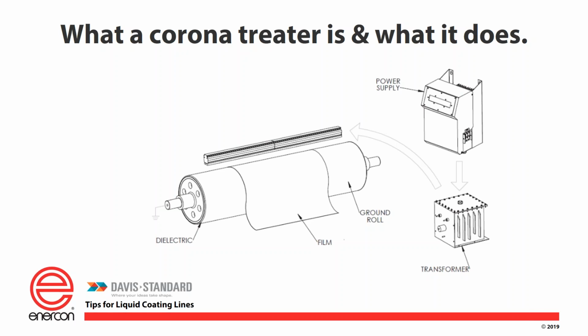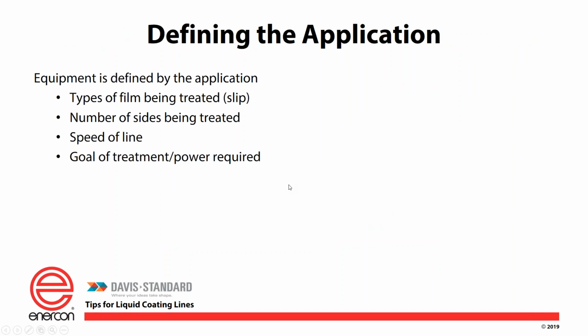And the end result of that is an increase in dyne level. So for example, in a pre-treated polypropylene, you might get that material coming from the extruder at maybe 36 dynes, let's say. And then after that 36 dyne material passes through the corona treater, it can actually increase the surface energy to maybe 40 or 42 dynes, depending on various conditions. But that's really what the corona treater is doing, is ionizing air. That ionized air then creates a functional surface on what otherwise is a non-functional film. Next one, Mark.